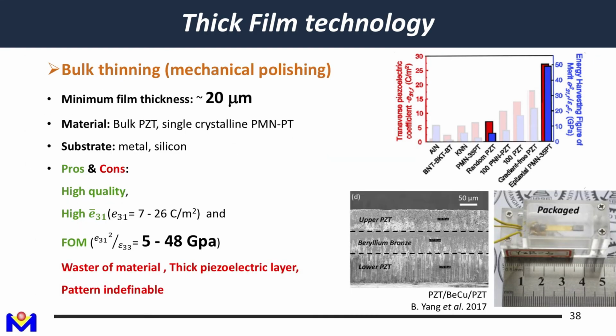Okay, then this process is the other thick film technology. It's using the bulk material sintering, and although in theory you can get a figure of merit of about 48 gigapascal as general bulk PZT material, as I just mentioned, when you thin the film, you will generate cracks inside. The percentage will be higher, so the overall figure of merit is actually degraded. If you want to have a very thin film, then possibly it's not possible lower than 20 micron.